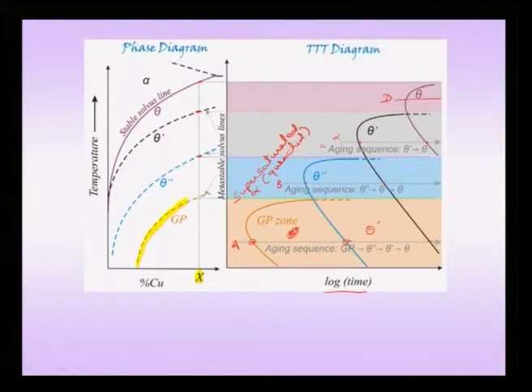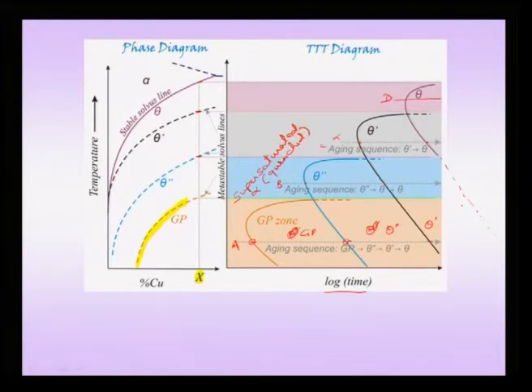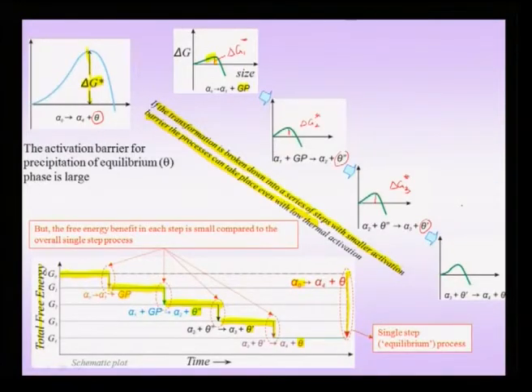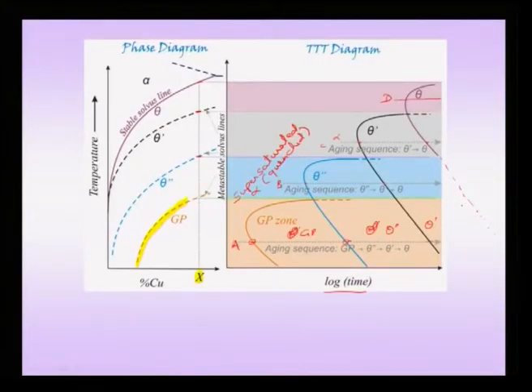There are separate curves for: alpha to GP zones, GP zones to theta double prime, theta double prime to theta prime, and theta prime to theta. Using extended phase diagrams and the simple concept of activation energy together with extended TTT diagrams, we can understand how aging at low temperature gives a series of metastable phases instead of equilibrium theta directly. The aging temperature matters because it determines how much activation energy is available for the system to adopt a structure that, though metastable, gives benefit in activation energy.